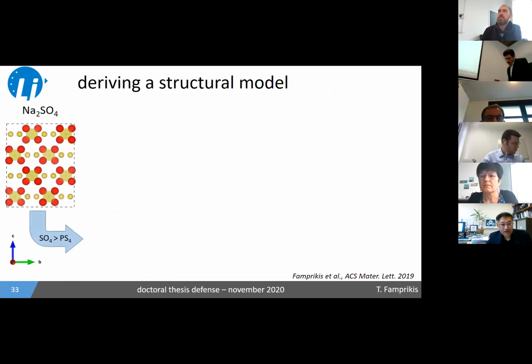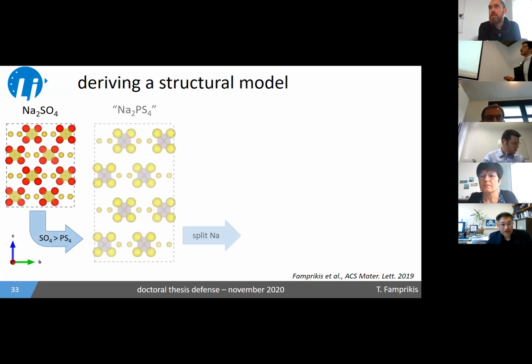This was quite challenging, but the key observation was that the electronic density, once Fourier transformed from the diffractogram, points to large similarities with another material that crystallizes in the Fddd symmetry, namely sodium sulfate, shown here. And if we simply take the structure of sodium sulfate, replace the sulfate by a thiophosphate, and expand to our observed lattice parameters, we get a very plausible structure that initially has a decent preliminary fit to our peak intensities, let's say. So going from here, basically we only have 2 sodium, we need 3.